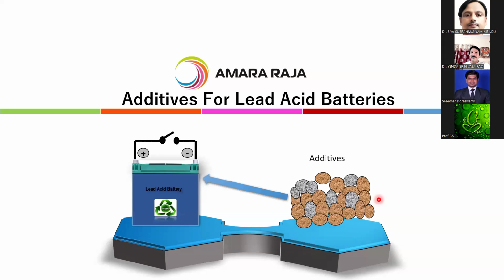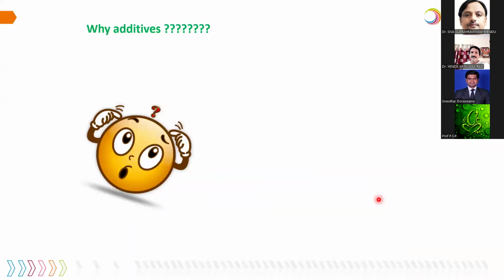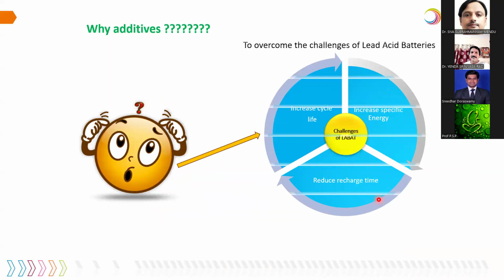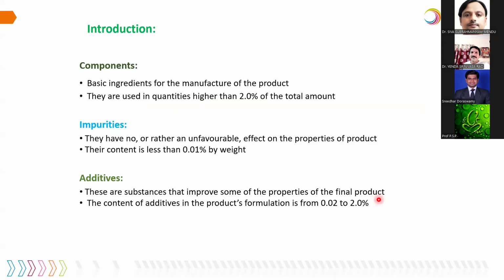Now coming to additives role, these additives are primarily focused upon the active material additives. So as we know, the active material here is lead oxide, and to improve the utilization rate of those active material, that means increasing the span of the activeness of those material, we require some additives. So normally these additives are 2% in weight, have been used either in positive or negative as the maximum, and the impurity should be less than 0.1%.